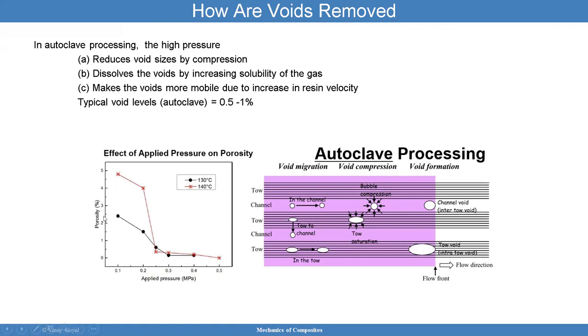But you can see here the porosity percentage, and I'm talking about porosity that is directly correlated to void content, how much void I have within the composite. And so the more voids I have, the more porosity I have, and I'll explain later how that's measured. But the bottom line is the more pressure I apply to the sample, the more benefit I have in terms of removing those voids, and the porosity is dropping.